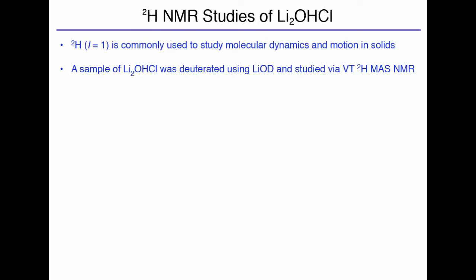So in NMR, one of the things we can do is specifically choose a certain nucleus to study if you think that you have a type of motion. And because we know that there's some motion in the lithium and some motion in the proton, we can actually manipulate the proton environment so that we can look at it more closely and see what type of movement's occurring. And to do this in NMR, you typically use deuterium NMR because it's well known and well reported for studying anything that's to do with dynamics and motion. So we were able to deuterate a sample, so basically put this 2H into the sample of Li2OHCl using deuterated lithium hydroxide, and then we could study it as a function of temperature.